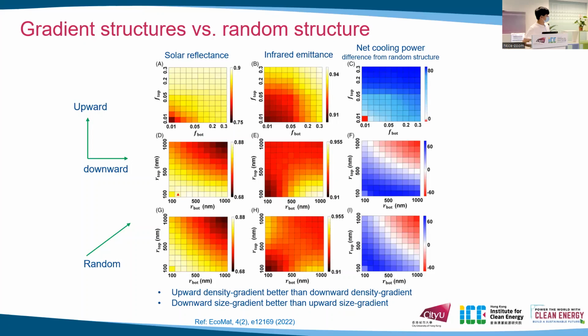The first row is for density gradient, and the second row is for size gradient. And the y-axis is for upward gradient, and the x-axis is for downward gradient. We can see that for the density gradient, the upward direction has a better performance because this solar reflectance is higher than this one. And the infrared radiation does not change a lot. But for the size gradient, we can find that the downward direction has a higher solar reflectance than the upward, and also has a higher infrared emissivity. So it can achieve a better cooling effect compared to the random structure.